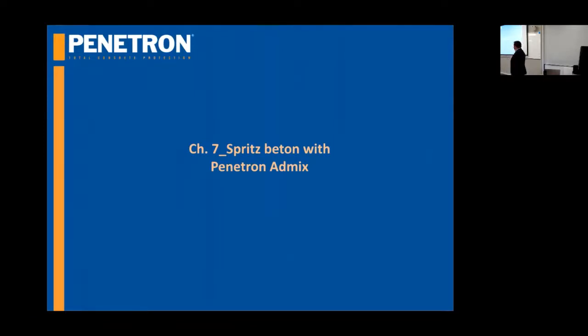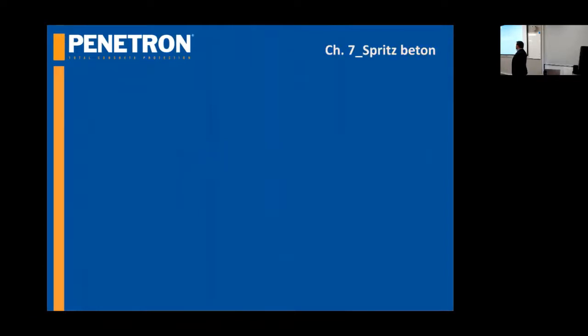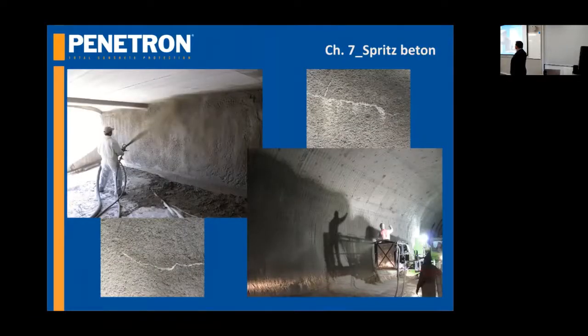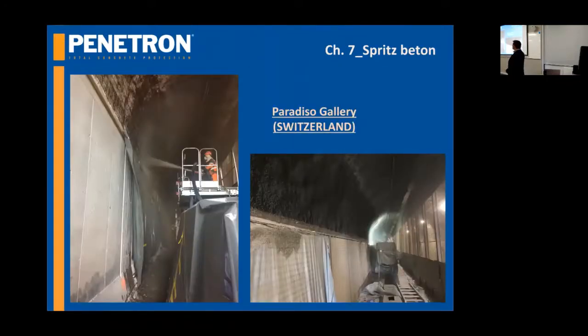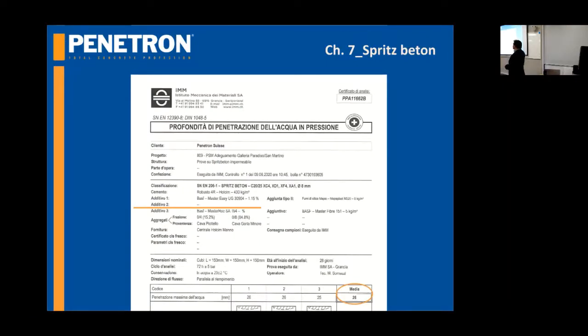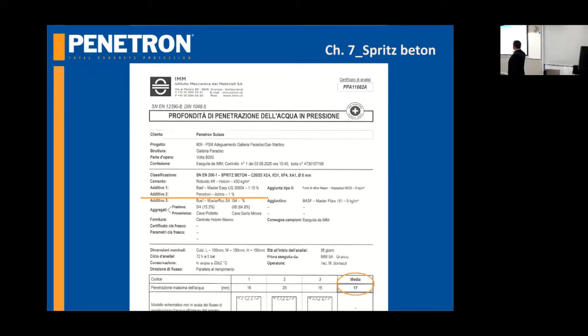The next chapter is concerned with spritz beton with Penetron Admix. Spritz beton is an application very used in tunneling and in all conditions where you need a smooth surface for next workings, or maybe just to finish it. So for example, this is a gallery, Paradiso, a site in Switzerland, and we decided to make some more tests on this site. We made a test with the concrete without Penetron, and we got a permeability of 26 millimeters. The same concrete with Penetron inside got a permeability of 17 millimeters. This means that it doesn't reach the embedded steel, and it's a very good result.